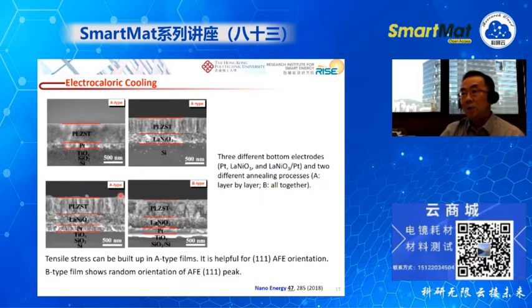This thin film is processed by the sol-gel processing, multiple layer deposition. So in the A-type processing, we deposit the film layer by layer. Then after deposition of each layer, we do the annealing. In the B-type deposition, the strategy is we deposit all the layers, then do the final annealing.